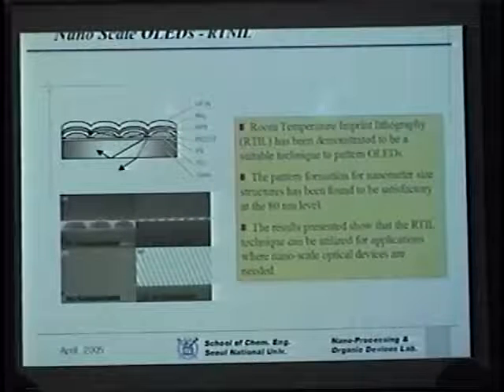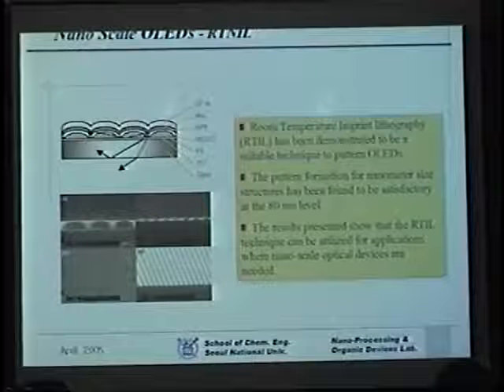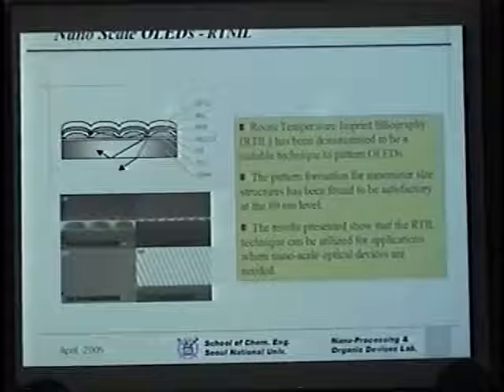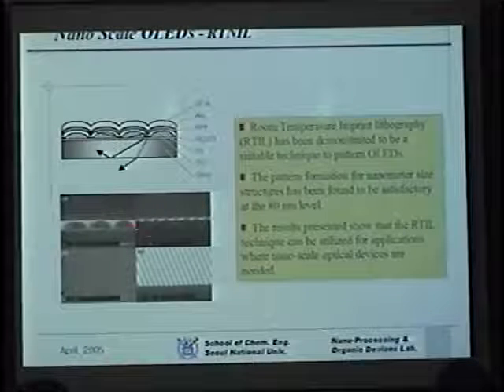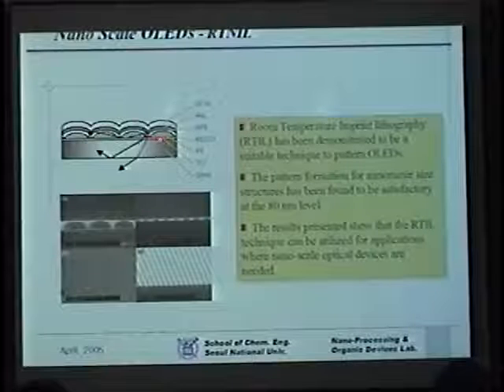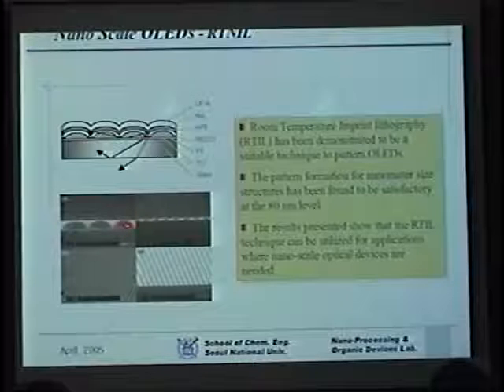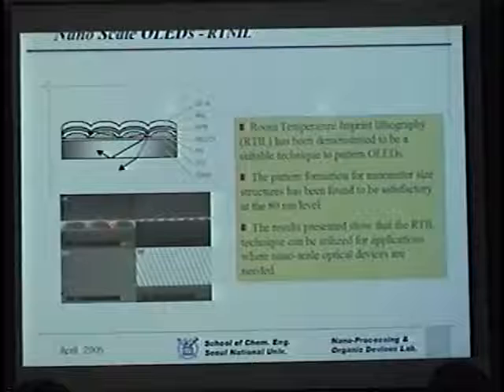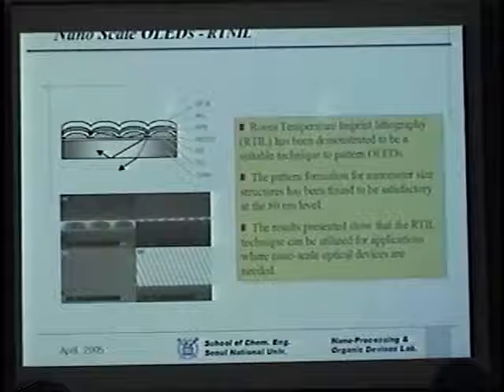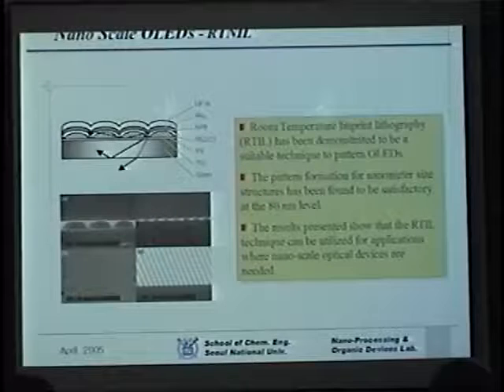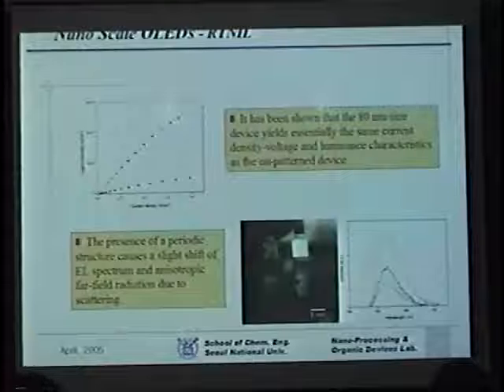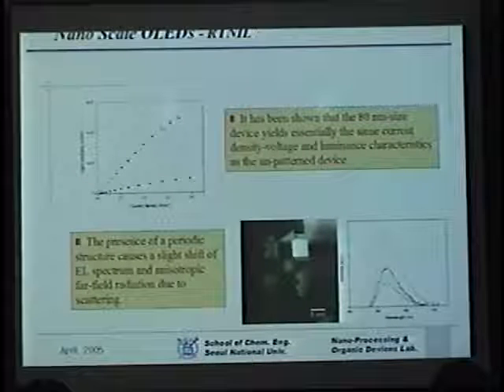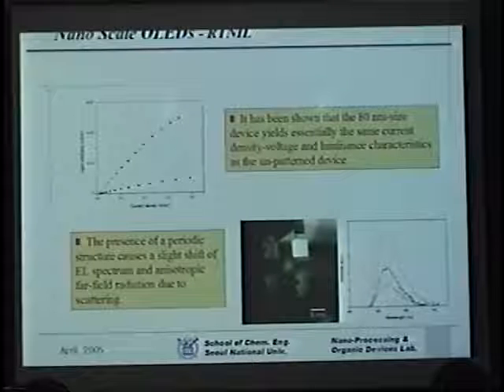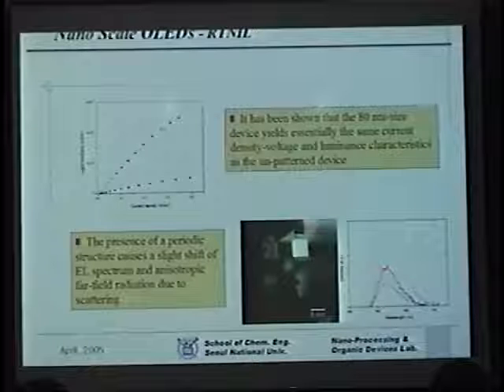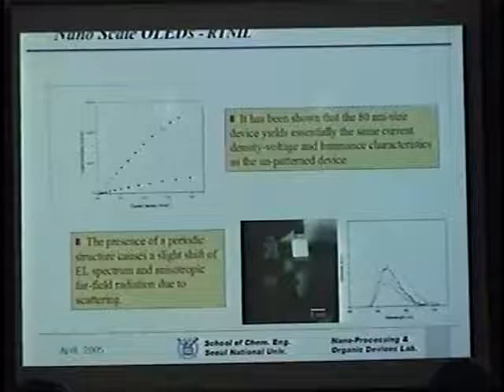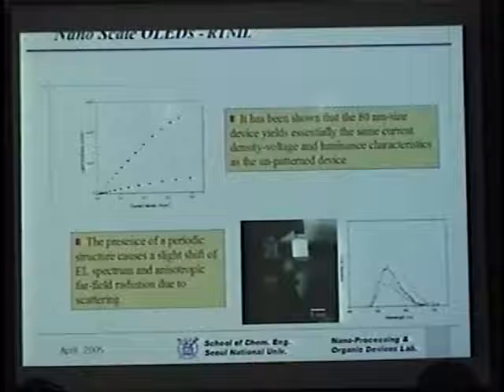Another question we had along the way was whether a small device would function just like a big device. In this case, we made it by patterning this polystyrene layer, acting as a barrier here and forming an 80 nanometer device in this gap. And we found that this 80 nanometer scale device would function exactly like a big device, but we found some shift in the EL spectrum, and this is probably due to scattering taking place along the zigzag type patterning done.